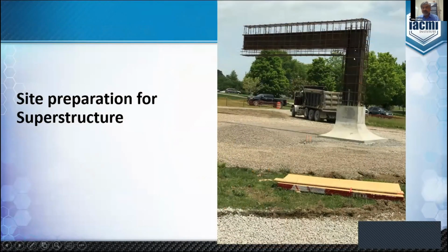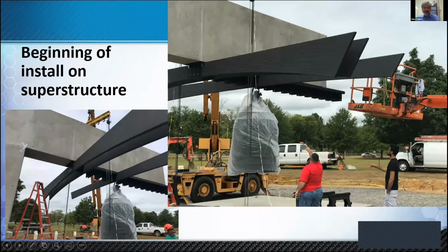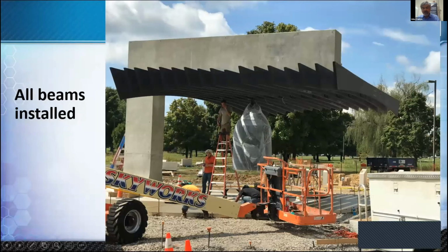This is the superstructure here. It's essentially like an L-shaped structure. Each of the beams would be located in this position with the fixture that I just showed. For example, as the beams start getting mounted, you can see they're each located in a very unique position based on their arc radius out here. And then the bell is positioned right in the center. This L-shaped structure holds 8,000 pounds of the bell, and then very light beams that hang over it at the end of the day. So this is how the complete assembly would look at the end.